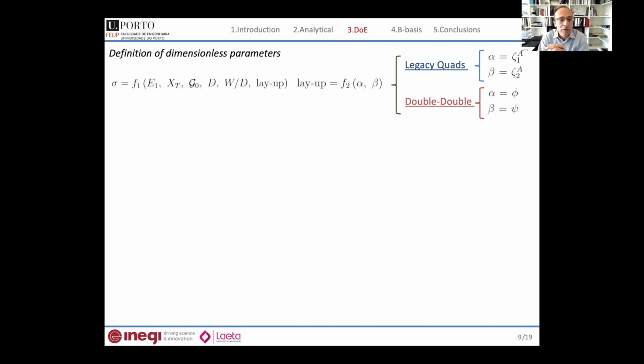Okay, so then we have to define the parameters that we're going to use in the sampling and then in the machine learning process. And you can see that using fracture mechanics, we can predict the strength based on 7 parameters. So Young's modulus, strength, fracture toughness, hole diameter, specimen width, and layup that corresponds to 2 parameters. So for the legacy quads, Xi1 and Xi2, for the double-double, the 2 fiber orientation angles. But we want to do better than this because we still have 7 parameters, and of course that would require a large data set to properly train the model, okay? So we want to optimize this.